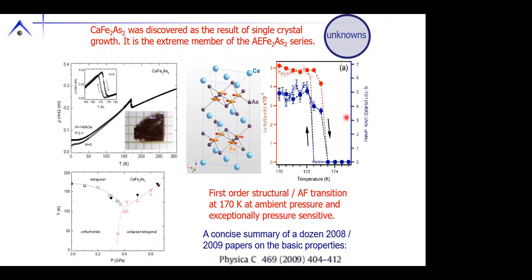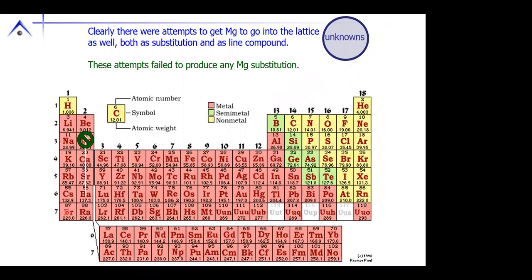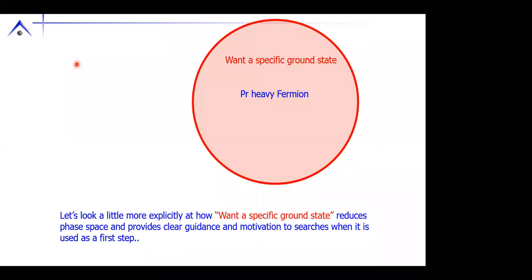It has strongly coupled first order antiferromagnetic and structural transition. In addition, if we apply very modest pressures, we can go from a tetragonal to a collapsed tetragonal phase, at which point we lose any hints of the magnetism or potential superconductivity. Now, of course, we can say, good, barium, strontium, calcium, what about magnesium? Well, sometimes when you ask nature a question, the answer is no. So we asked, does MgFe2As2 form? And the answer was an unequivocal no, both for my group as well as several other groups that I have interviewed about this material. All right, now that's sort of warm up to introduce the ideas.